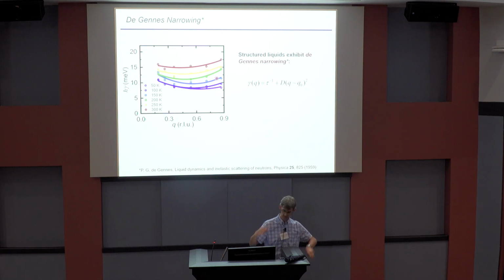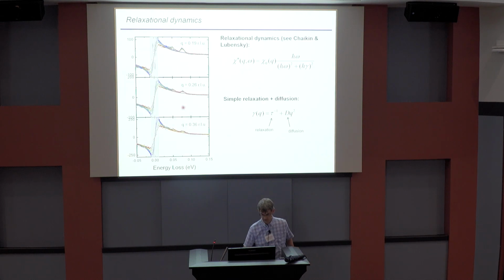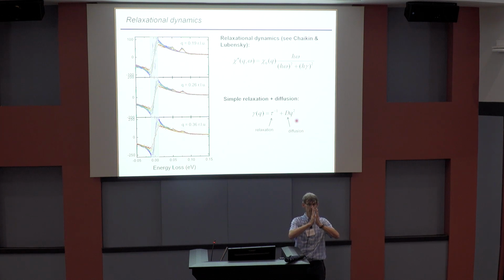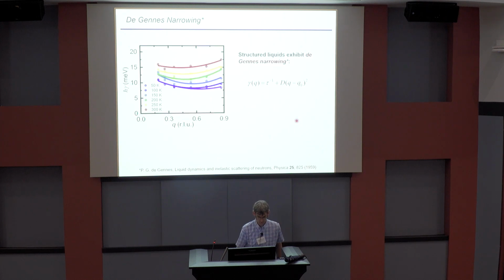So the background tau is quite temperature dependent, so that gives you this offset. And then the interesting thing is there's a minimum at finite Q. So in normal diffusion, this Dq squared implies that the gamma width is smallest at Q equals 0, and then as you increase Q, it gets wider. And that tendency gives you actually the diffusion constant, okay? So what we find is that this system has such a minimum, but the minimum is at finite Q,